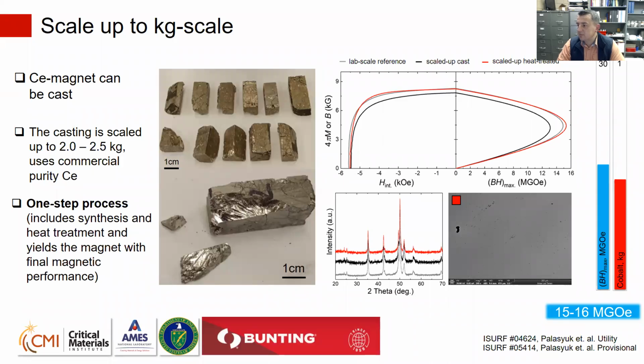Can you explain a little bit about the castability? What is extraordinary about that? You mentioned only ALNICO is made that way. Yeah, so castability is extraordinary because it's simple. It avoids crushing, and it avoids making small particles, and it avoids oxidation of the particles. And if you could do it in one casting step, then you avoid all the processing with powders. Since the coercivity mechanism here seems to be kind of intragranular, it's possible to cast this material, and it actually simplifies the processing quite a bit.